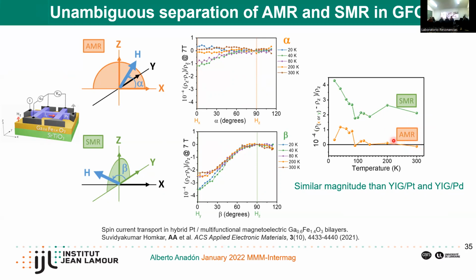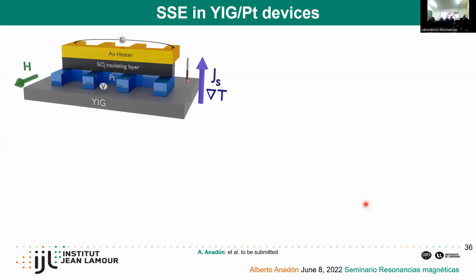And furthermore, we can take advantage of this material also for thermal devices. And what we did was devices like the one I'm showing here. Basically, we have our YIG thin film or GFO later on. We can grow a platinum layer on top of it. And then to measure its thermo-spin properties, we place a silicon oxide insulator layer on top of it, and then we grow a gold heater. So in this case, we can locally heat our sample, which is very interesting because it will allow us to have more reproducible measurements than in the case of full thin films.